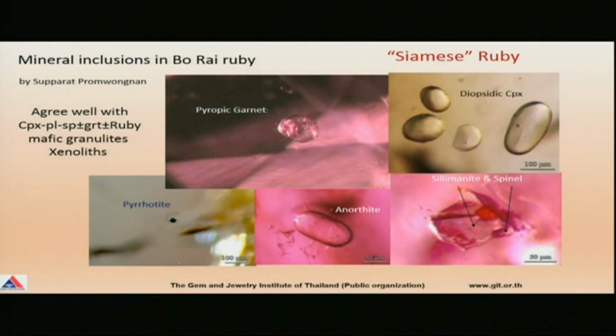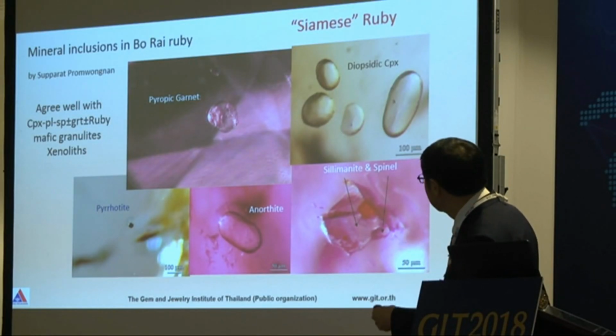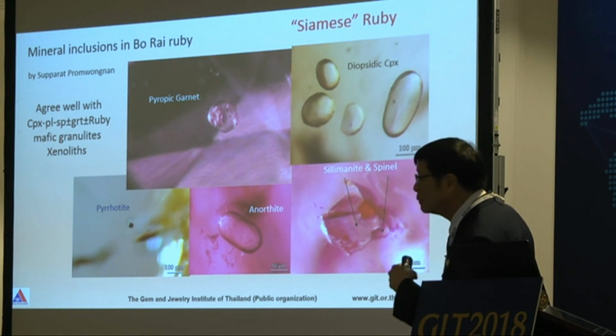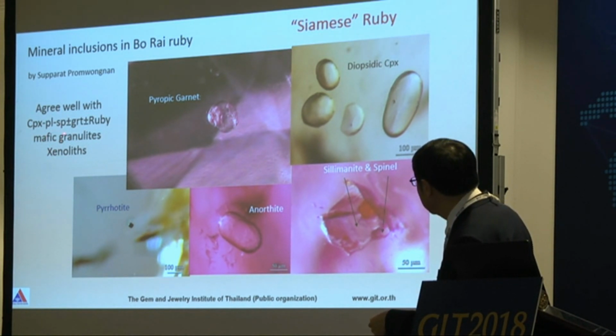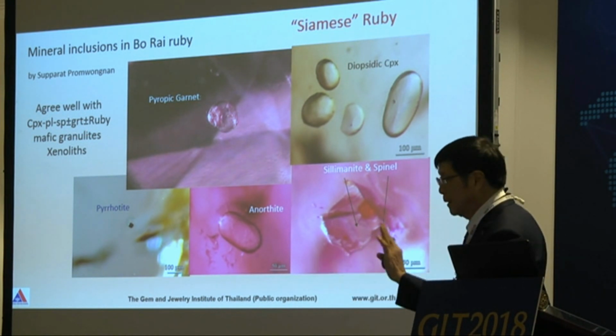And Supparat also found an interesting inclusion. She probed this inclusion, and we found it's pyrope garnet, pyropic garnet, and diopsidic clinopyroxene, some pyrrhotite, iron sulfide, and anorthite, feldspar, sillimanite, and spinel. So spinel is very special because it's an indication that it's a metamorphic type rock. And this mineral assemblage agrees quite well with the mafic granulite xenolith that had been found. So mafic granulite is composed of clinopyroxene, plagioclase, spinel, garnet, and ruby. So it fits perfectly.